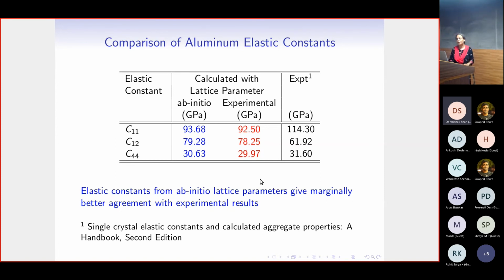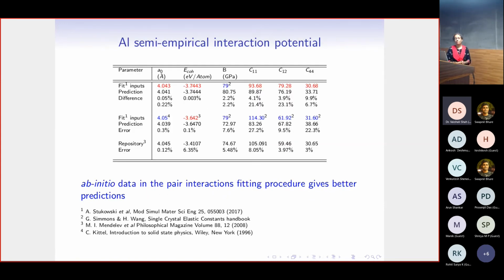So it looked like the elastic constants that we were getting from the ab initio predicted lattice parameters were giving us a slightly better agreement than when we started from the experimental lattice parameter. As I said, the reason we did this is because we put this into the fitting procedure for the interaction potential. What you see in the red here is the input that we give to the program that is going to do the fitting of the parameters and generate the semi-empirical potential for us.